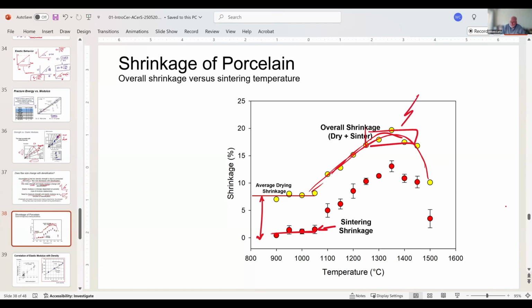This is my firing range for porcelains, at least for this porcelain, okay? And then if I overfire, my density decreases because of bloating. So if I looked at this, these are dried. I would expect that as I start to heat treat this, I degrade my network. I would expect my strength to decrease and then increase as I start densifying. So I would expect sigma to increase here, to be a constant here, and I would expect it to go through a minimum down here.